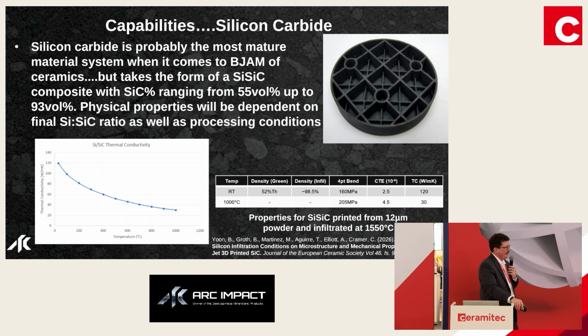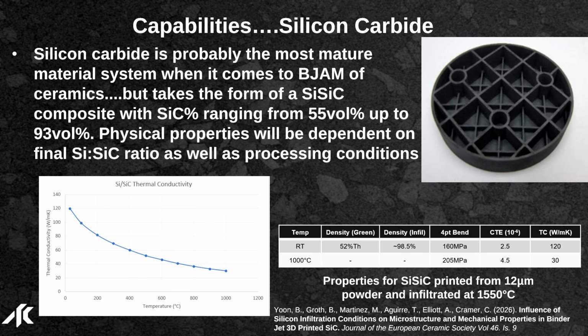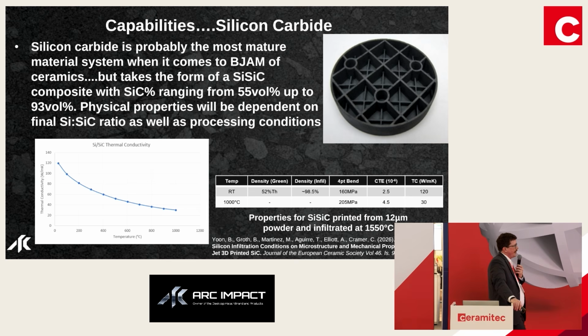So one of the more mature systems out there, and again, what you've probably seen as you walked around the conference hall, are these silicon carbide parts. This is the back of an optical mirror. And when you're printing silicon carbide, you're actually ending up with some sort of composite in the form of siliconized silicon carbide, where your silicon carbide percent can vary based off of your processing, both your print processing and your post-processing. And typically you'll see up to 93 volume percent silicon carbide, where you're filling in the rest of that porosity with the silicon. You're using that as a filler to show that you're 100% dense.